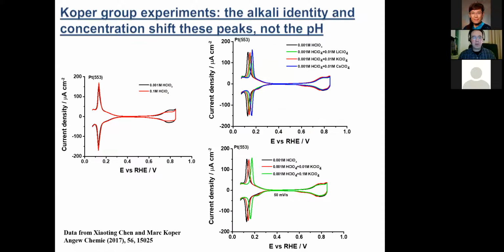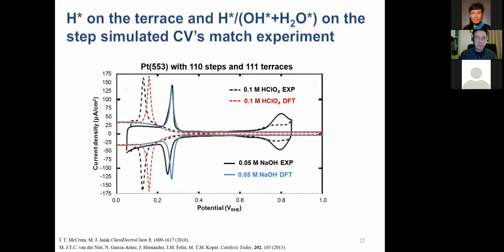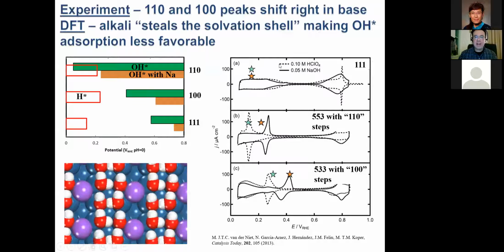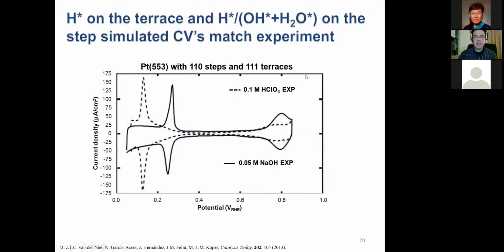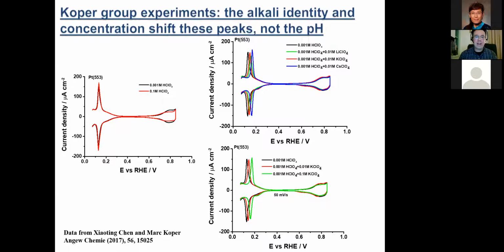We then worked with Marc Koper's group, who looked at, instead of changing the pH, changing the cation concentration, because these peaks were thought to be shifting not because of the cation, but because of the pH shift. He showed that if he changed the cation concentration without changing the pH, the peaks shifted. So it really is the fact that the cations are being added that's leading to these peaks shifting, not the fact that pH is changing.